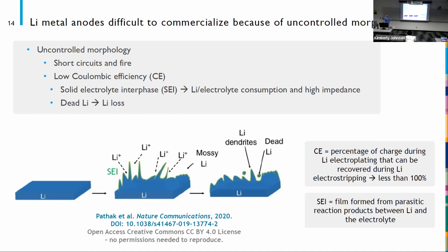We typically measure with batteries the Coulombic efficiency. That's basically the percentage of charge that we put in during electroplating that we can recover during electrostripping. So we plate some lithium, and then we try and strip that lithium away, and we don't get all of it back usually.